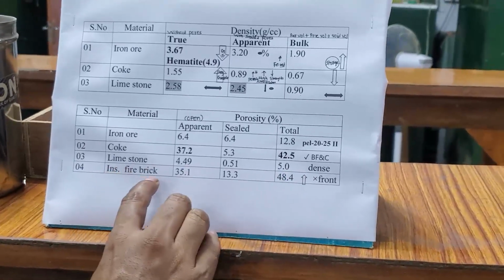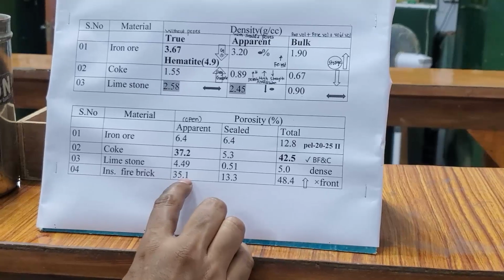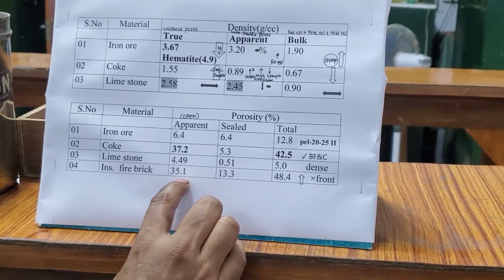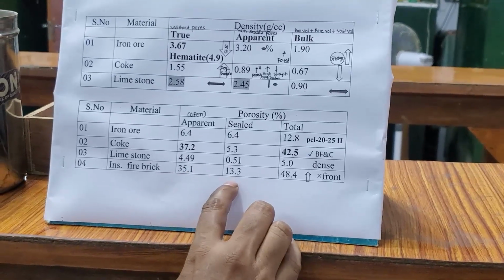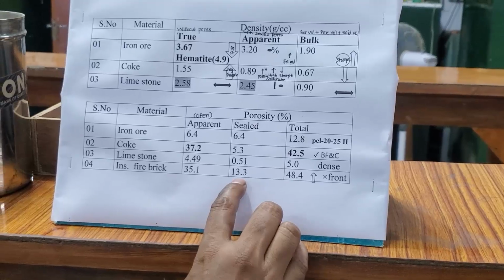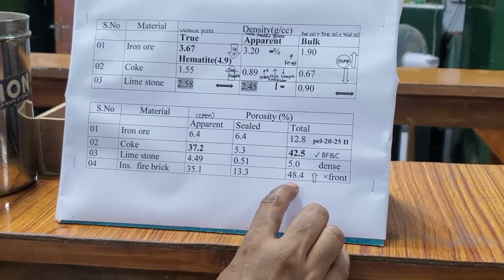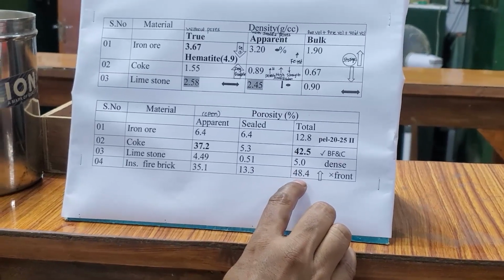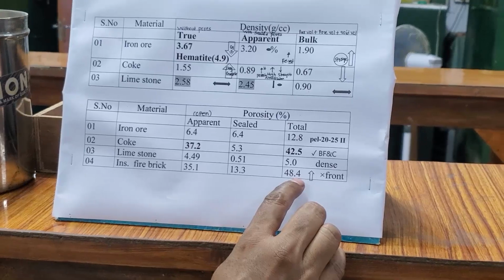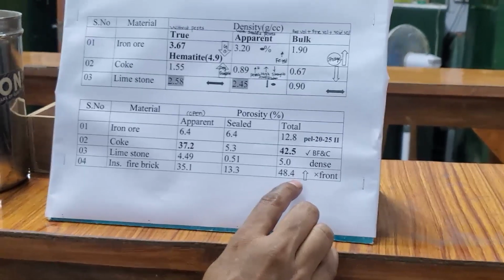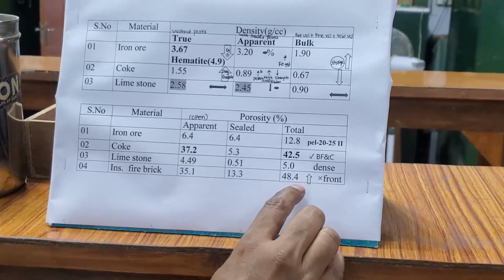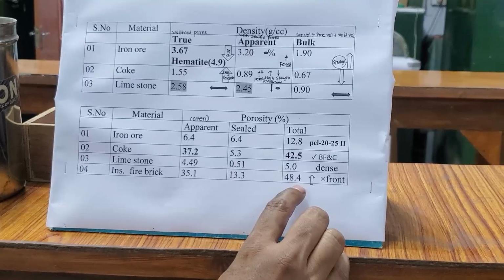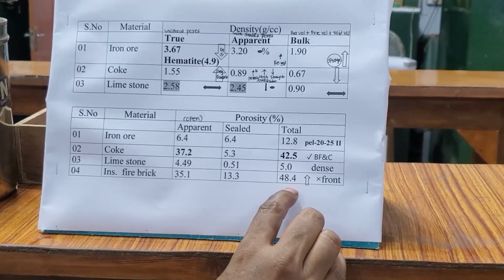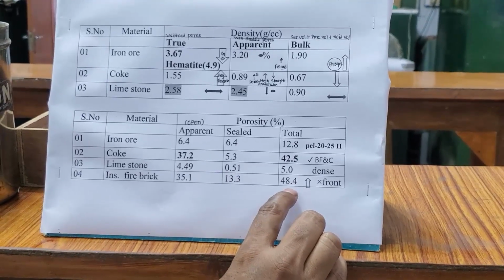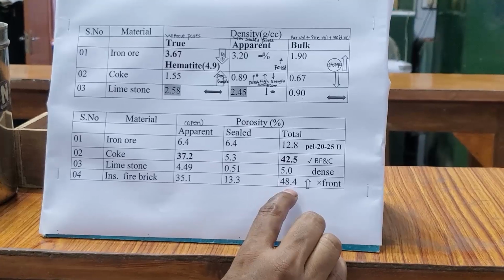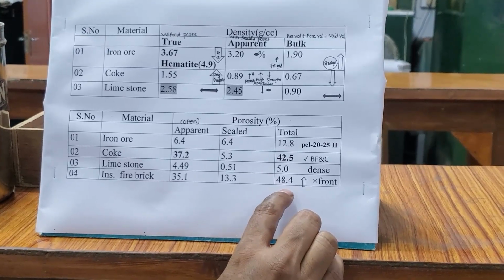In case of insulation fire brick, we can see the open porosity is more, that is 35.1, and sealed porosity is 13.3. The total porosity will be 48.4. What it indicates is that this brick has more porosity, more pores. What will happen if we use these bricks as a front lining? Then the metal and slag will enter into the brick, and the bricks will fail. So we should not use them.